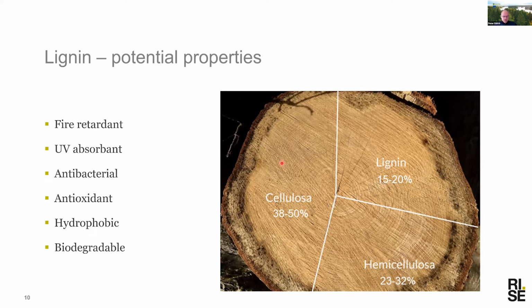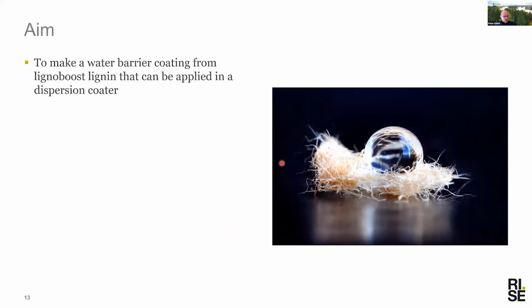It's fire retardant, it's UV absorbent, potentially antibacterial and antioxidant, hydrophobic as long as you don't dissolve it in alkali, and it's biodegradable. So we have all the boxes here that we really want. We have some boxes that we wouldn't want. It's quite brittle too. But this comes to the aim of the work we have been doing, and that is to make a water barrier coating from lignin that can be applied in a dispersion coater.